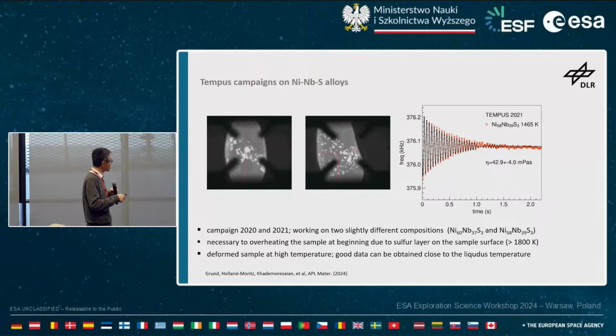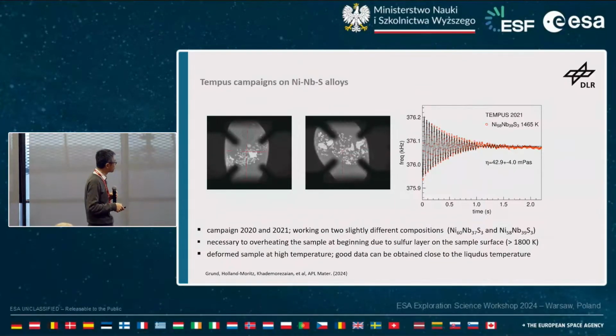What we found is that we learned a lot from this parabolic campaign. One more technical thing is that if you look at the melting process, you find that at the beginning one still has a lot of solid, if you want, at the sample surface. This was later figured out to be due to the sulfur layer at the surface. Due to that, we need to go at the beginning to a relatively high temperature in order to dissolve it completely. That's why we cannot measure at high temperature, because due to the heating, the sample deforms a lot. And we can only do good measurements when we supercool the sample once and cool back to a relatively low temperature, so that the sample is quiescent.